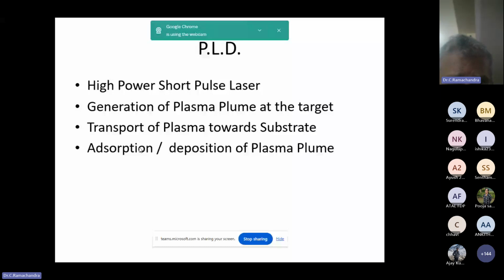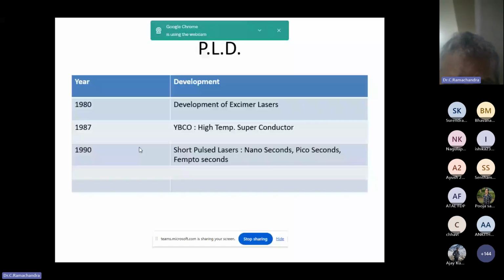Some of the developments: in 1980 we could develop the excimer laser, that is the beginning, and in 1987 we did high temperature superconductors using this technique. In 1990, systems were developed with pulse widths of nanosecond, then picosecond, and femtosecond. Today we have pulsed laser systems with femtosecond lasers, such a short duration. In femtosecond, one atom cannot make any difference from another. Such high power energy comes in such a short time that every atom gets ablated. There is no time to even transfer the energy to the neighboring atoms.